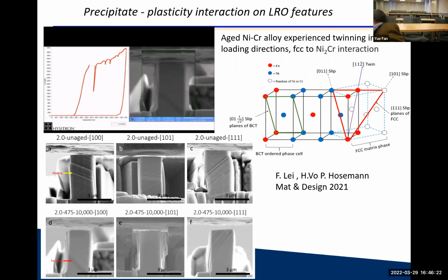Now, it turns out that there's an orientation relationship between the long-range ordered feature and the host matrix. And in almost all orientations, you can do that slipping and not change the stacking order, except if you apply the stress in one orientation, then you would have to create an anti-phase boundary. That costs you a lot of energy. In that instance, the material rather starts twinning than slipping. And so your deformation mechanism actually changes. So in that instance, you can dial in what deformation mechanism you want, depending on which orientation you push it, which is kind of interesting.